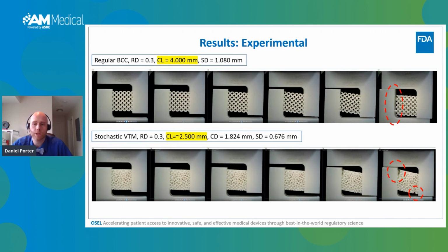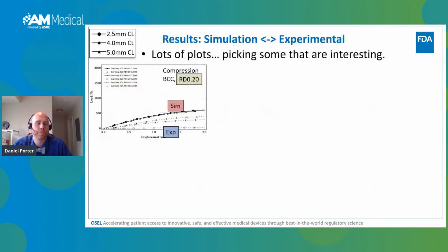Another thing to note is that the time-lapse images before failure show that the lateral movement on the grips seems to be negligible. So maybe that assumption of completely constraining the plane in the FEA was a reasonable assumption. It's one of those things where you have to verify. So you can see that from there.